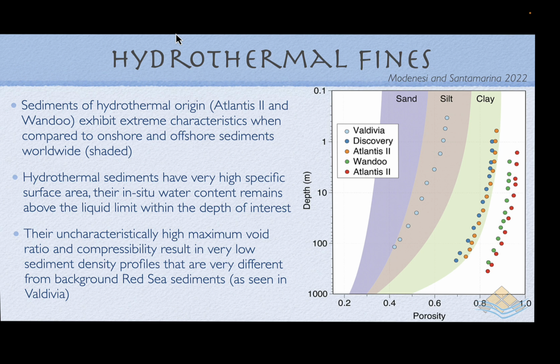Because of their ultrafine grain size, they have very high specific surface areas, and so their in situ water content remains above the liquid limit throughout the upper 20 metres where metalliferous sediments are accumulating in the Atlantis II Deeps. This uncharacteristically very high maximum void ratio and compressibility result in very low sediment density profiles. And these are very different from the density profiles we measure in background Red Sea and other sediments, such as